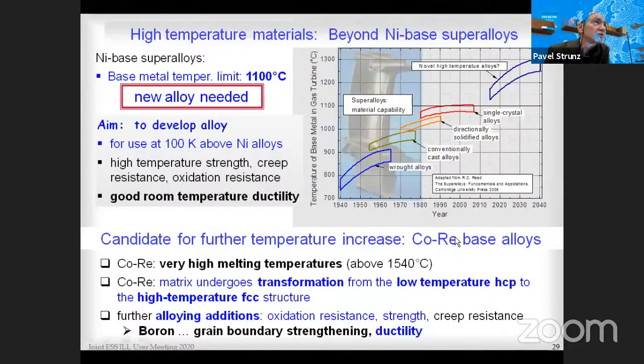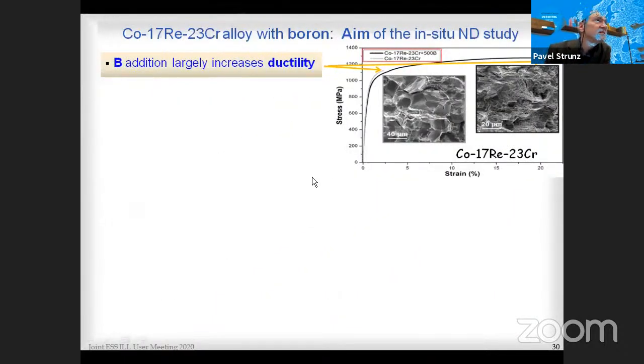One important point for cobalt-rhenium alloys is that they are hexagonal at room temperature, and they can undergo transformation from low-temperature HCP to high-temperature FCC at some point. Alloying additions provide oxidation resistance, strength, creep resistance, and ductility. But I'm going to talk about boron addition, which provides ductility. It works. You can see that with zero boron addition there is such low ductility. With 500 ppm, there is such a large increase.